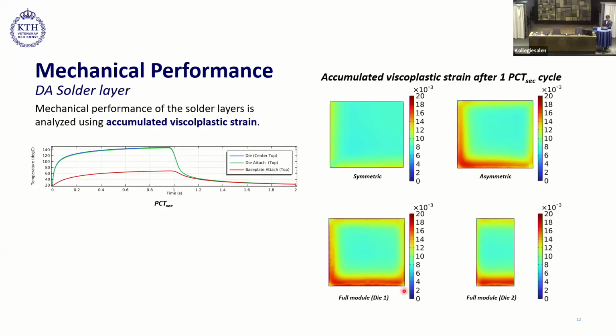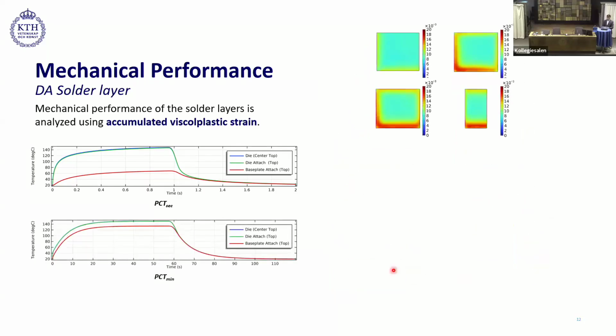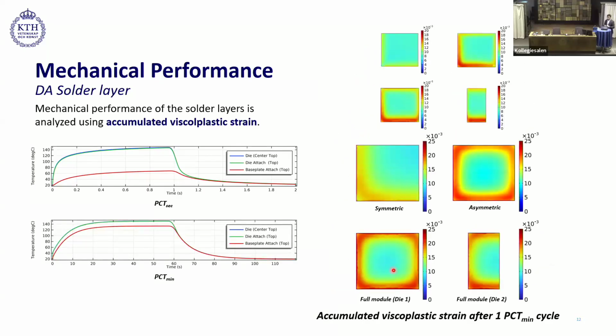One important thing to note here is that this area, which is also closer to this parallel die, also exhibited a bit high viscoplastic strain accumulation. So we see that the location of the die and the number of dies that are connected in parallel have an impact on the viscoplastic strain accumulation. If we compare it with the strain accumulation during PCT-min, then we observe that during PCT-min, the strain accumulation was a bit more uniform around the edges, as we see in the asymmetric and the full module condition.